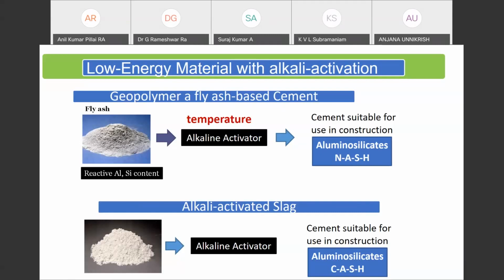The other alkali-activated material we're talking about is alkali-activated slag. That is, you start with slag, mix it with an alkaline activator, and because slag contains a higher percentage of calcium, we produce a binder which is calcium alumino-silicate hydrate. So again, here there is no cement in use. It's a binder made completely out of slag. So these are alternate forms of binders that we are starting to experiment with.